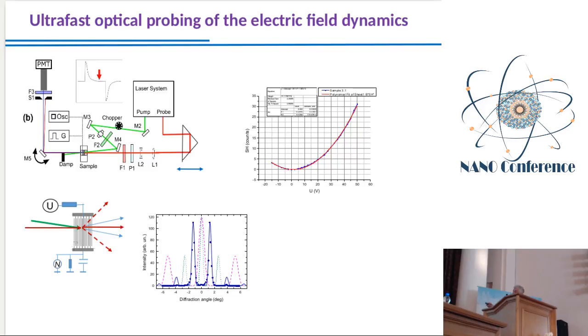So here we also have a diffraction grating, and so when we apply an electric field, our laser pulse diffracts into different directions, and the second harmonic diffracts to some particular direction, so it's here. Okay, so now if we apply another strong pulse, so here is like a probe pulse which probes the electric field, but if we apply a strong excitation pulse, we generate charge carriers, and these charge carriers, by moving through our sample, reduce the electric field. And in this case, we have this ultra-fast time resolution. Here is a setup. We have a probe pulse, we have a pump excitation pulse, we excite, and we look at the intensity of our diffracted beam.